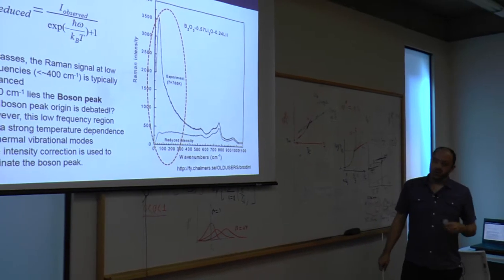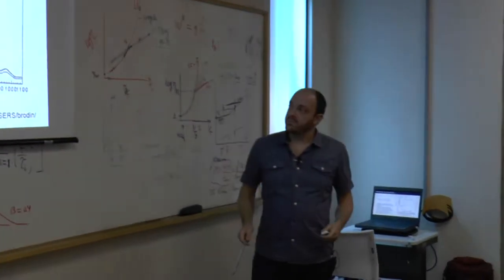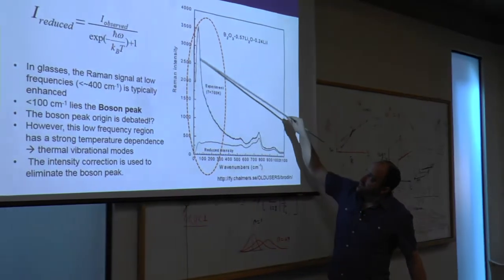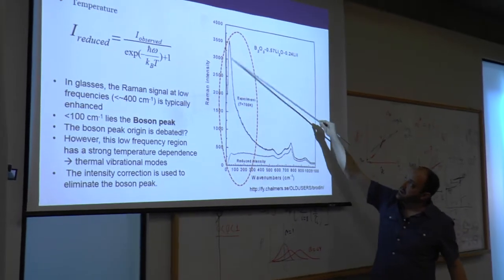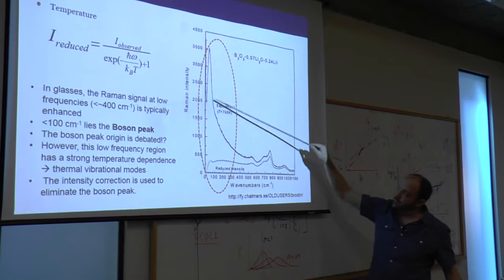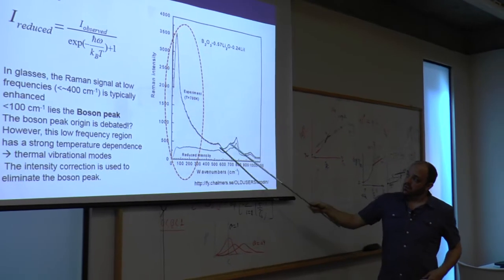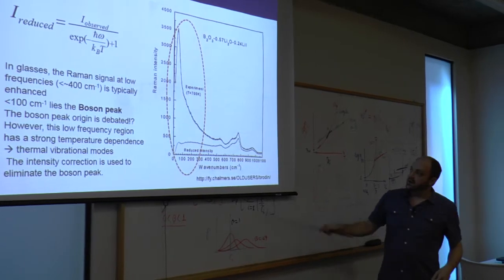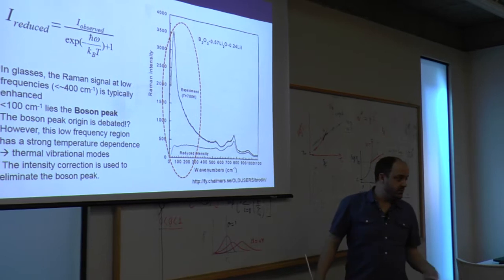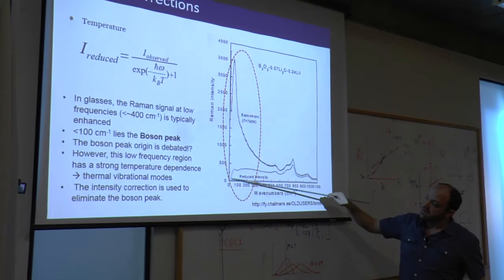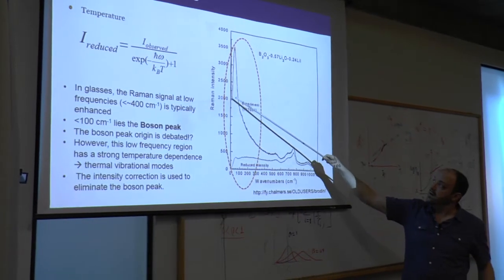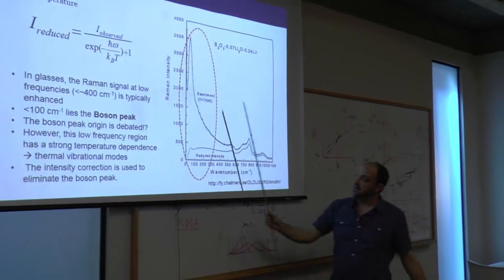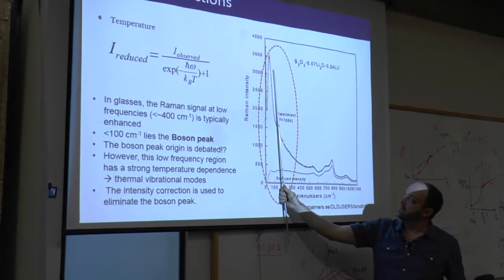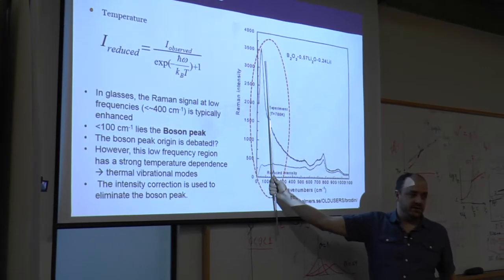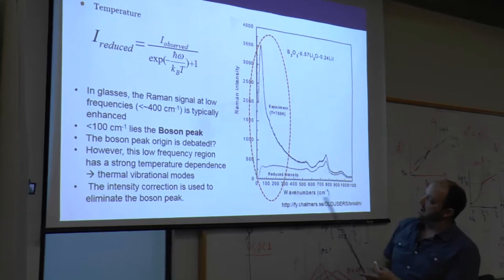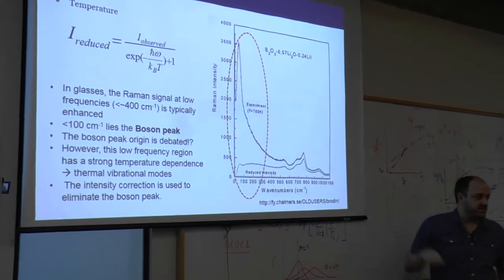A lot of people use a correction on the spectra. So you take a spectra and it looks something like this top one here. Most Raman spectra of glasses and amorphous materials have an enhanced scattering up here. And if you get a modern Raman system, it has nice edge filters or triple gratings, and you can get down really close to the wavelength. So this is around 10 wave numbers here. But the older systems, they couldn't get that far, so they rejected pretty much everything from around 150 wave numbers lower. So if you want to quantify the spectra and you don't know exactly where this line comes, you have to make a guess about where is flat in your sample.